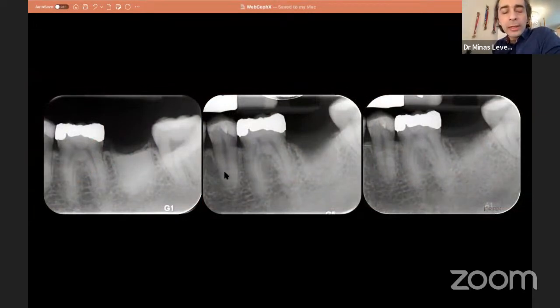This is what happens radiologically. This is immediately after placing my synthetic beta-tricalcium phosphate paste. We can see that after a month, it starts remodeling. So the graft dissolves. That's why it looks less radiopaque. And at the same time, we have the formation of osteoid, which is not very radiopaque. That's why at the first stages, it looks like the density of the area is not very good. But when it starts getting more mineralized, we can see here after 4 months how nicely we have regenerated the hard tissues in this very big socket. This is after 4 months.